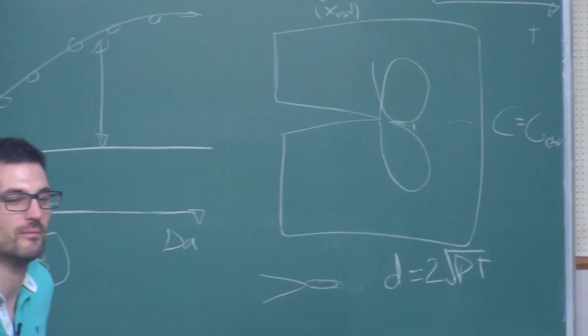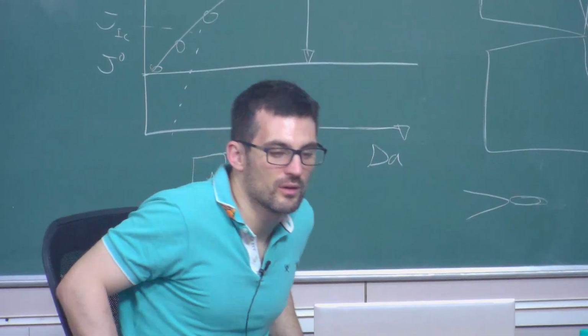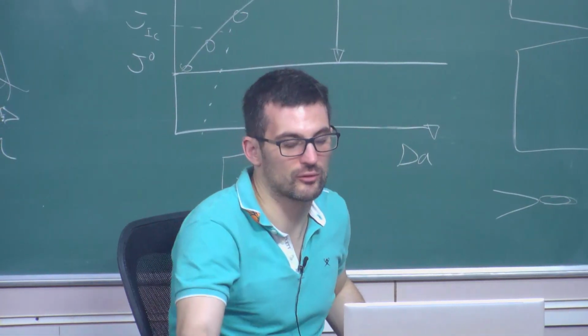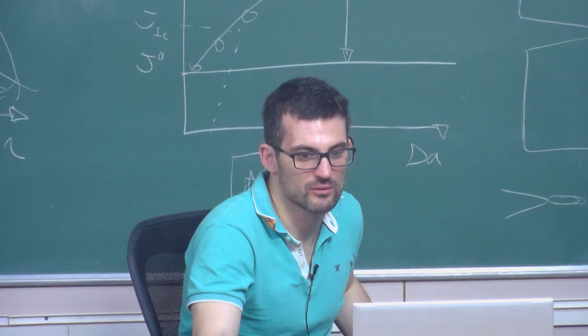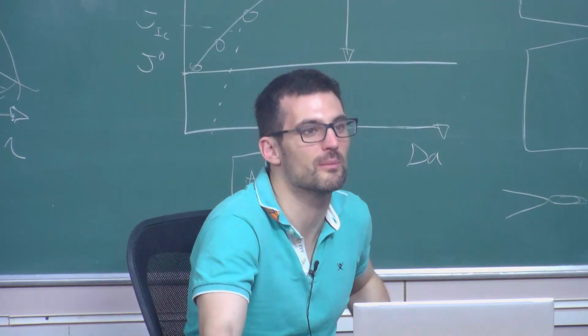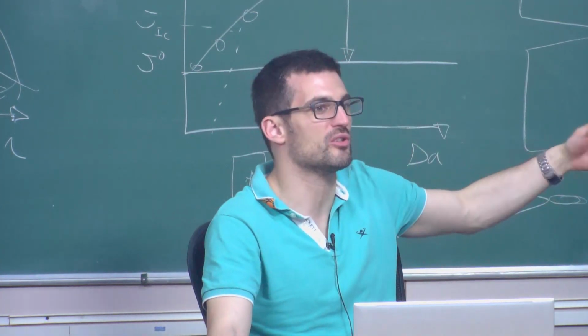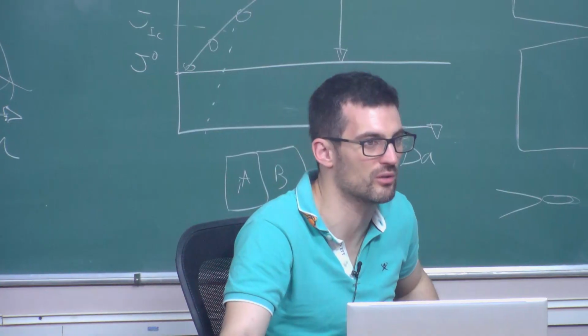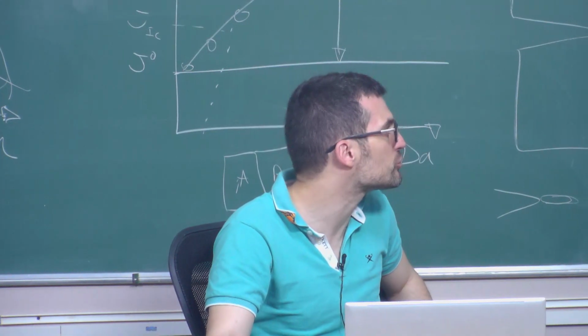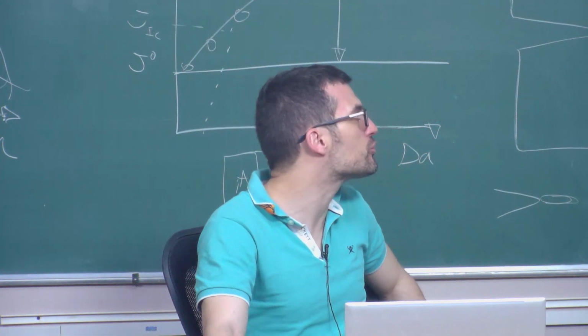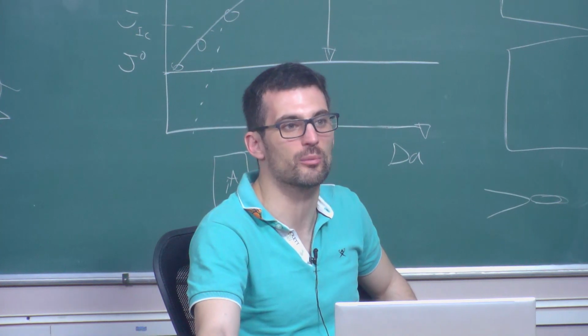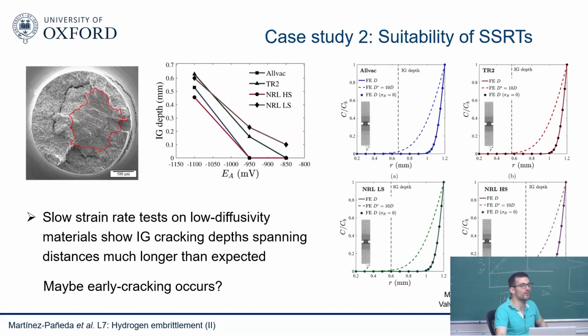What was the environment that this experiment was performed in? This is an electrochemical environment. I think it's a sodium chloride environment. Well, it doesn't really matter that much, but they apply a negative potential, cathodic protection. I think this is the most used test in the hydrogen community: slow strain rate test in an electrochemical environment, because it's the easiest to do when you think of mechanical and hydrogen. You need a cell, but otherwise it's straightforward.